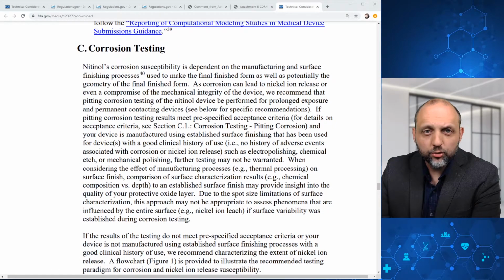In terms of corrosion testing, nitinol's corrosion susceptibility is dependent on the manufacturing and surface finishing processes used to make the final finished form, as well as potentially the geometry of the final finished form. As corrosion can lead to nickel ion release or even compromise of the mechanical integrity of the device, FDA recommends that pitting corrosion testing of the nitinol device be performed for prolonged exposure and permanent contacting devices. And there are some recommendations below.